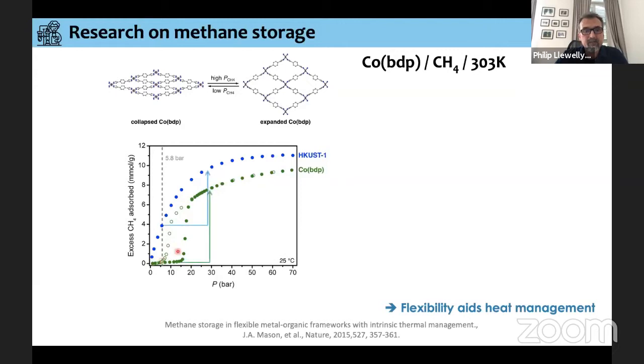The interest of this is that if we look at methane storage, for example for cars, we're looking at a working capacity between a lower pressure and a higher working pressure. For example, we can look at around 6 bar and around 30 bar, and we can see that this is the working capacity for this material here, and almost double the working capacity for a flexible material. And almost all the working capacity is used in the material, whereas we lose this part here for HKUST-1. So this flexibility gives us maybe an advantage in terms of working capacity.